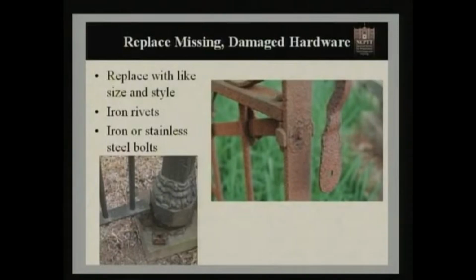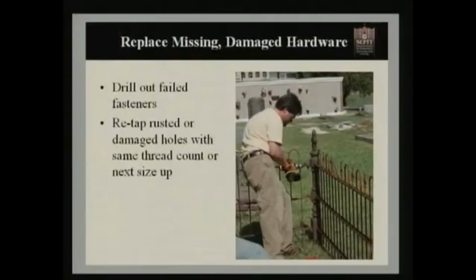We also want to replace the iron bolts if possible. Iron bolts are still available, or if they're not available in your area, we can go with stainless steel bolts for the replacements. Now, to do that, what we want to do a lot of times is drill out the failed fasteners. We also want to re-tap rusted or damaged holes. And if at all possible, you want to stay with that same thread count. Unfortunately, a lot of times when these rust, the hole opens up and expands. So in that case, you would want to go just the next size up. We want to try to keep from drilling any larger hole than we have to.